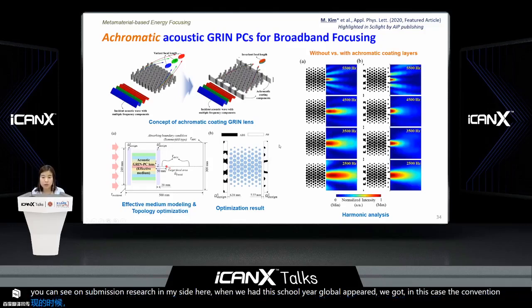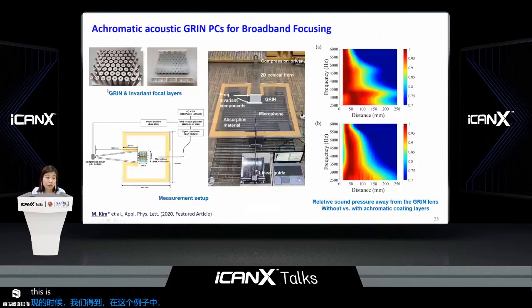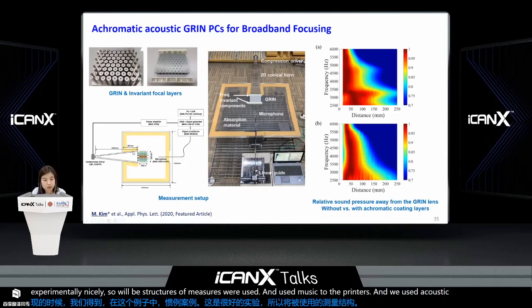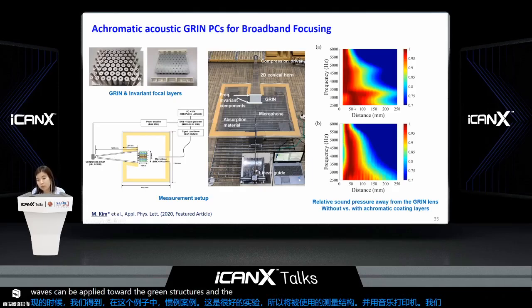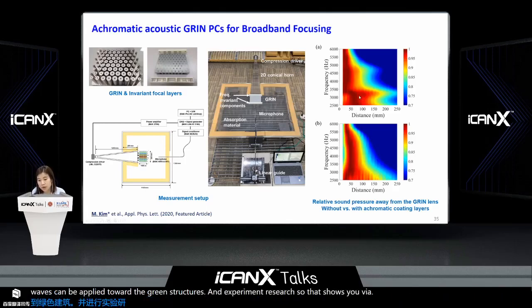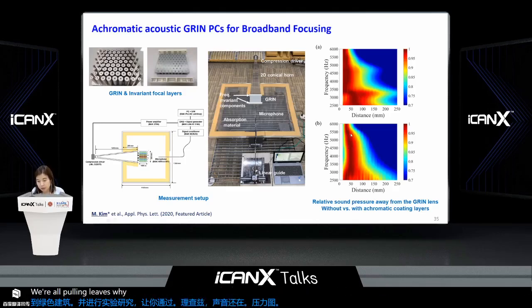And this is experimentally observed as well, nicely. For the GRIN structures, acoustically rigid material, aluminum, was used. And for coating layers, we use ABS using 3D printers, and we use the acoustic waveguide to make plane waves that can be applied toward the GRIN structures. And these are the experimental results. The top shows the relative sound pressure map without the achromatic coating layers, while the bottom map shows the very achromatic behavior of the GRIN lenses with achromatic coating layers.